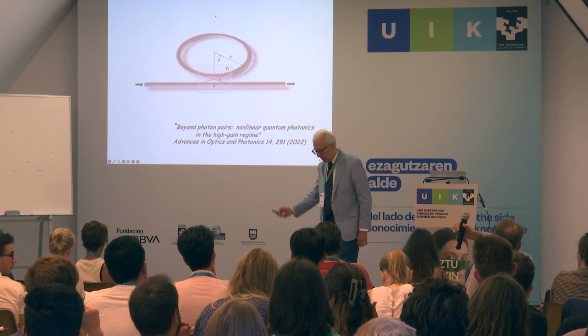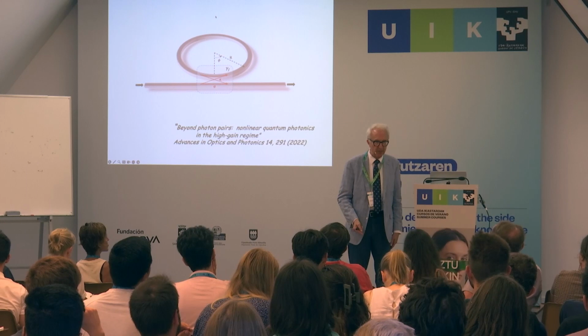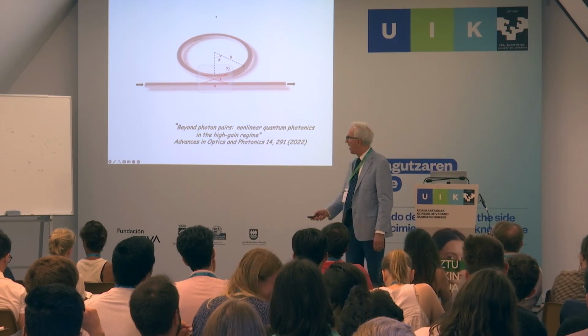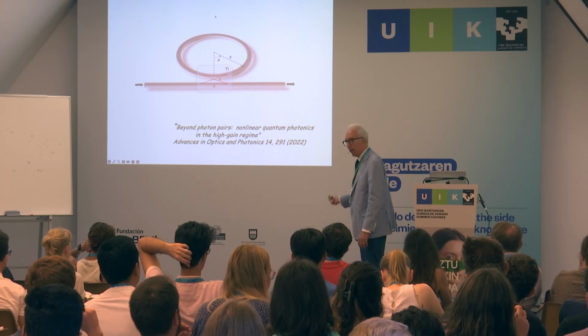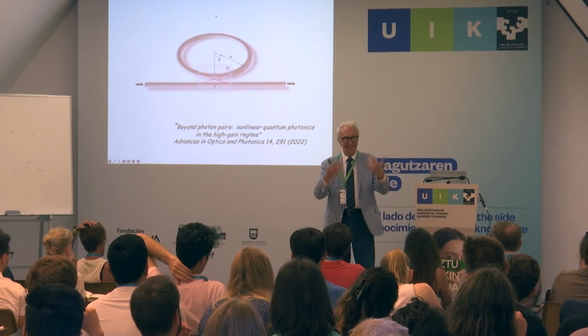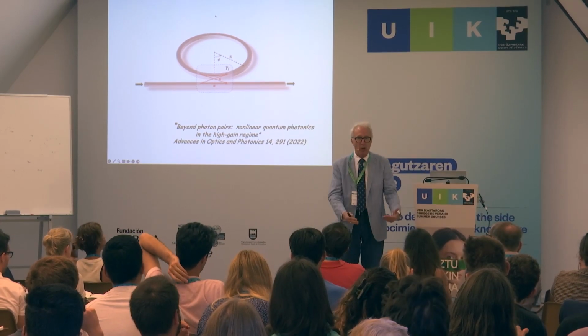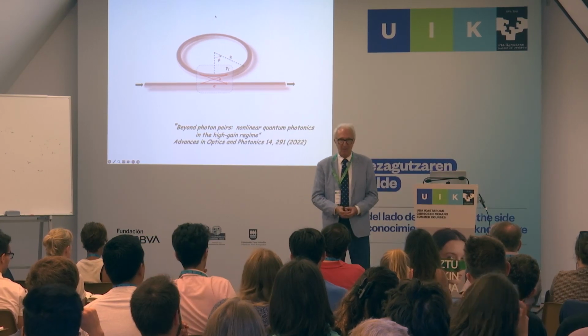In silicon nitride, the phonon scattering is also weak. That's another advantage of silicon nitride. The main problem is the scattering loss from the ring or from the channel waveguide, and that's why people have worked very hard at knocking that down, because in addition to a loss mechanism, that's a decoherence mechanism, which is a steeper price.